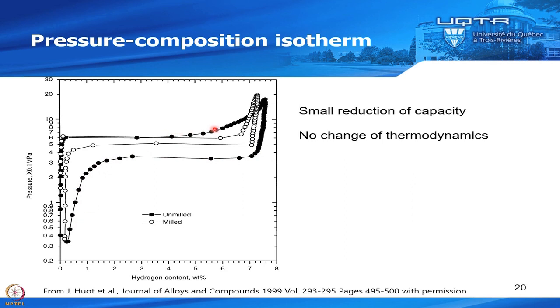So the plateaus on absorption and desorption are usually not at the same position. This is what we call hysteresis. But this hysteresis depends on many factors, but also on the kinetics. So you see that this is not a flat plateau, because here, in principle, at this point should be a stable point. Okay, so you should have equilibrium at this point.